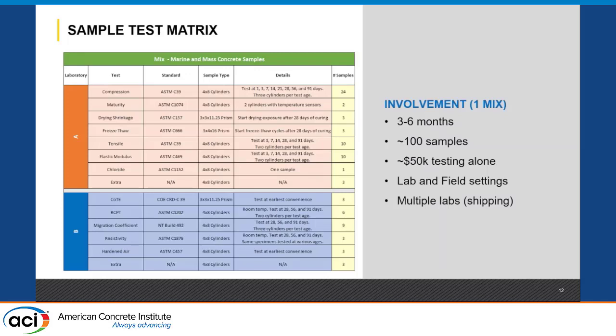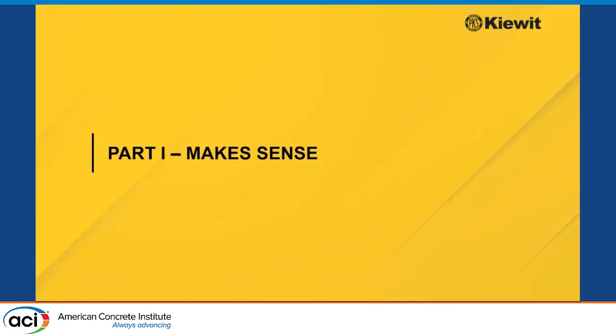There's lab and field settings. We have to use multiple labs, which involves shipping cylinders all over the country. Typically, we use different labs because if you look at these tests, they're very high-end for industry: RCPT, migration, resistivity, hardened air. So not every lab in the country uses that. And we use the local lab for your mechanical properties, your strengths, your elastic modulus, your tensile stuff, the boring stuff.